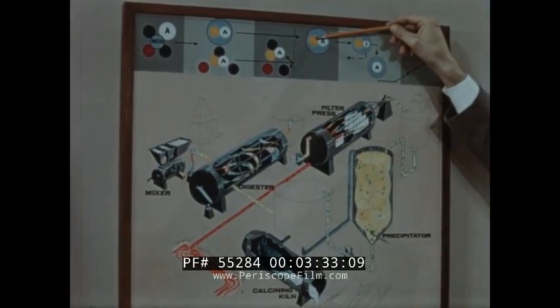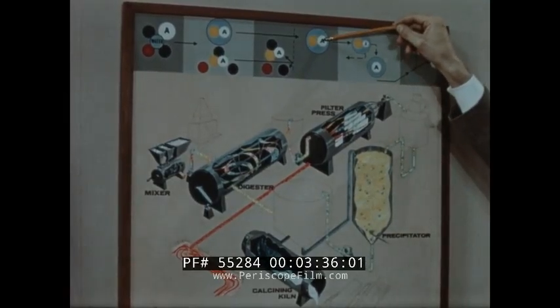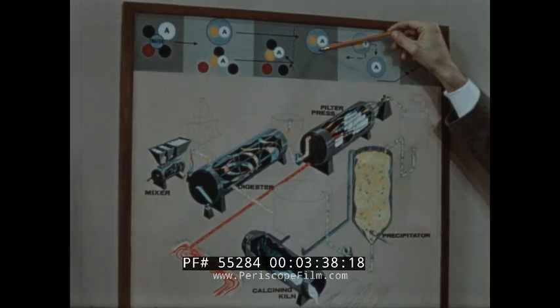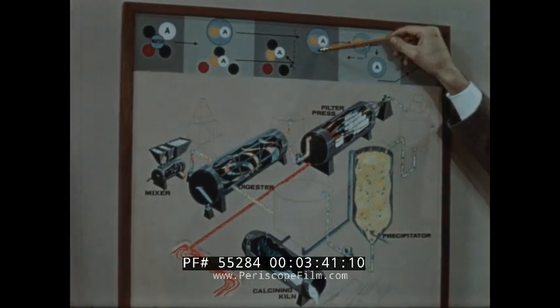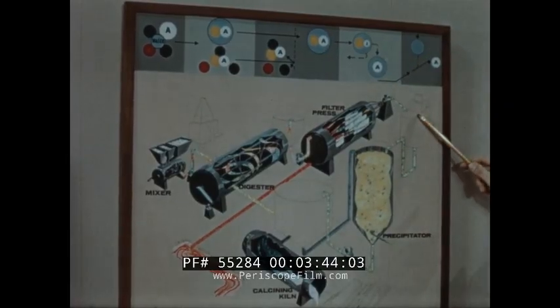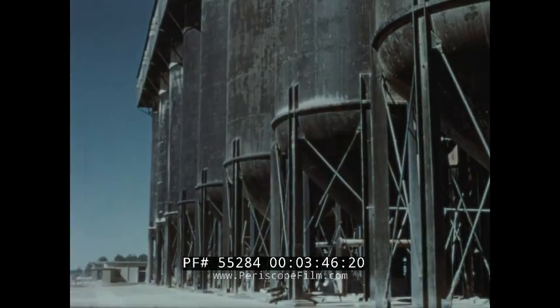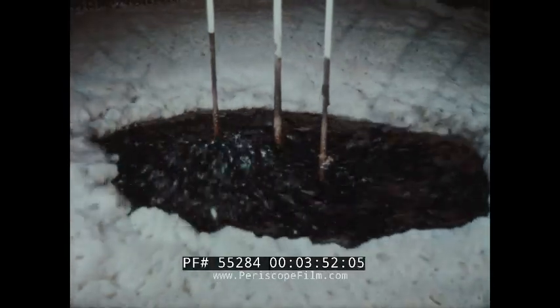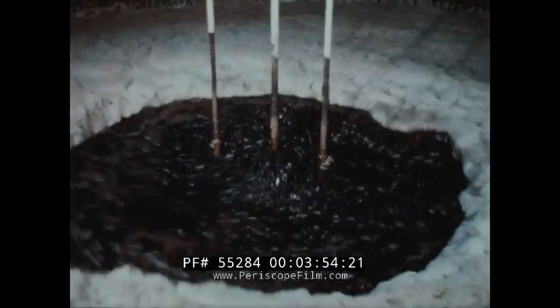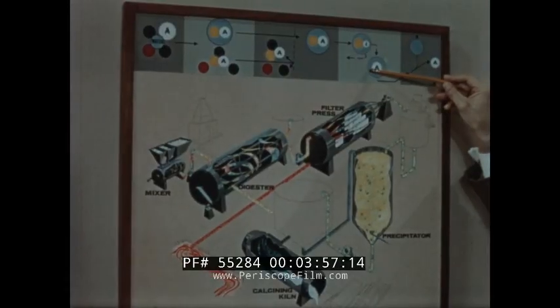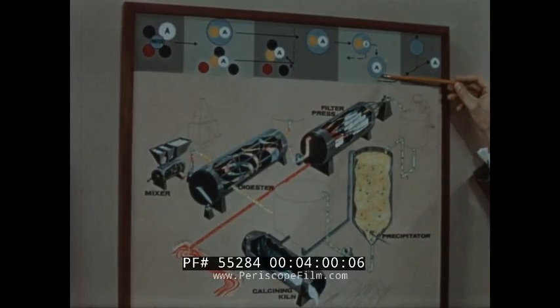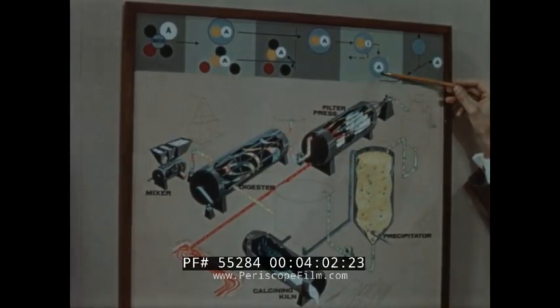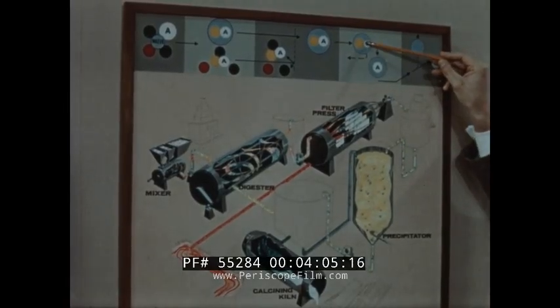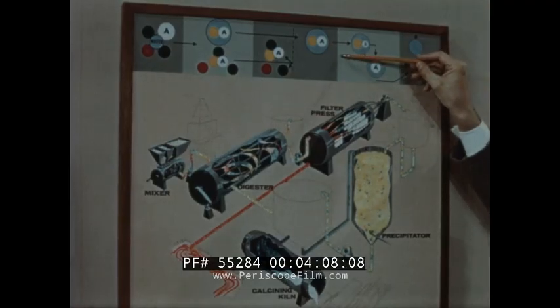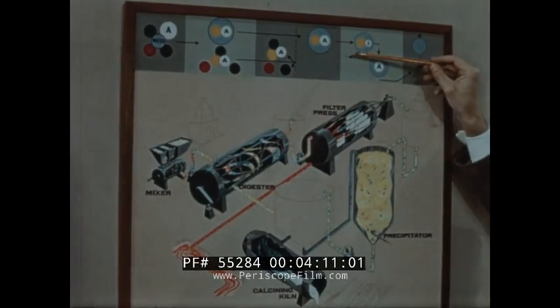This is made up of caustic soda and alumina and combined water. Our next step is to get rid of the soda. The solution then goes to a cooling tank and then into a large precipitator tank. Here it's cooled and agitated, and a seed of aluminum hydrate is used to stimulate the precipitation. The aluminum hydrate is essentially alumina and combined water. Now, when it's been separated, the caustic soda goes back into the system to be used again. Some dissolved alumina remains with the soda.